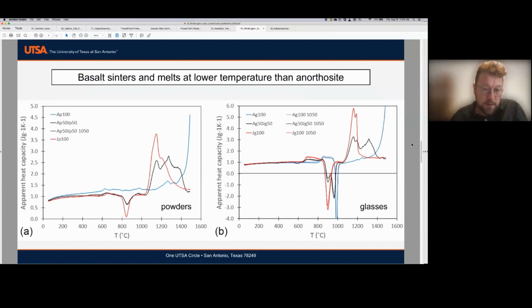We also noticed that basalt sinters and melts at lower temperatures than the anorthosite. So the mare are going to be easier, or at least work at lower temperatures than the highlands. So on the left, we see the powders, red is JSC, blue is anorthosite, black is a mixture of the two. And JSC is completely molten before 1400 C, and the anorthosite does not melt until well above 1500, actually slightly higher than our calorimeter can go. And on the right, you'll see actually the same is true even if we start with glassy starting material. So the glass transition temperature is lower for the basalt, and again, it's fully molten at a lower temperature than the highlands material. Next slide, please.